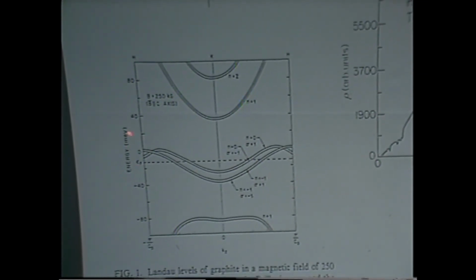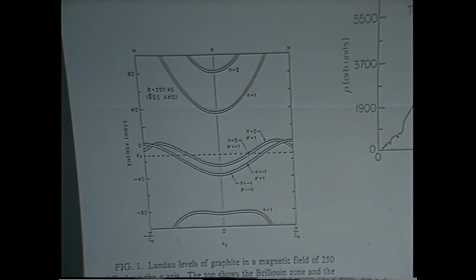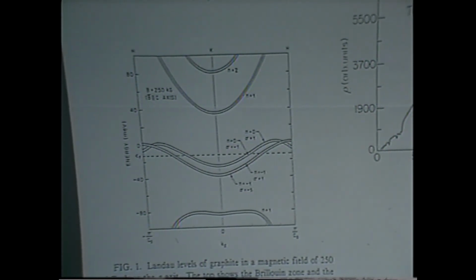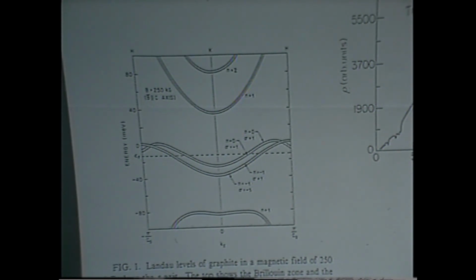Very, very surprising. Well, one explanation, maybe not the final explanation of this, is that you have a charge density wave instability that's set up because these bands that you see are sort of cosine bands and they're half filled. So this is a good system to have such a charge density wave instability set in, and that would have that functional form. Well, now all the bets are off, and this is still a field where a few interested people are working on this problem. This isn't high temperature superconductivity.